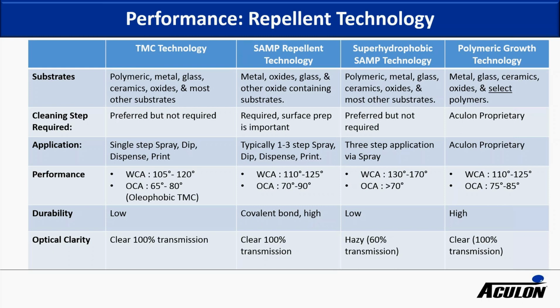And then lastly, we have this polymeric growth technology, which is very versatile. It has the ability to basically customize the properties of the surface. We're using the SAMP to initially prime the surface and then grow polymers with different types of repellent backbones off that surface. There is chemical bonding to the surface, so the durability is good, and they're still quite thin, usually somewhere between 10 and 50 nanometers, so you have good optical clarity.